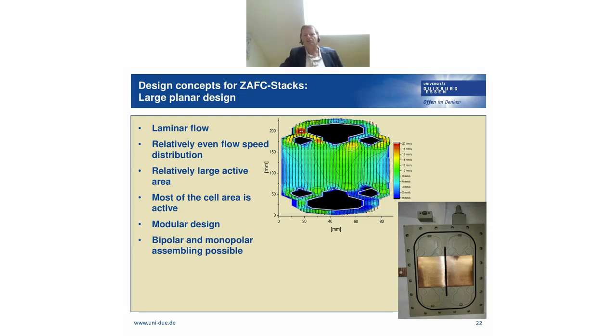We have here the current collector made out of copper, and on the bottom and on the top, we have the inlet and outlet of the zinc slurry. We have made it symmetrically to obtain an even flow speed distribution. This is important to avoid zinc sedimentation. And the picture above shows again the velocity distribution as obtained from PIV measurements.